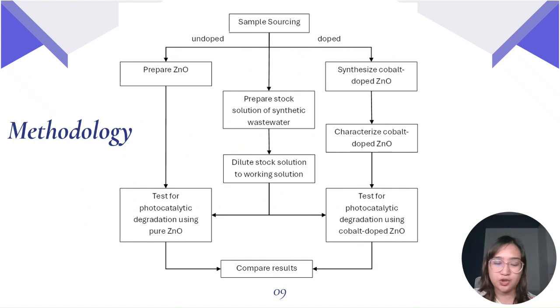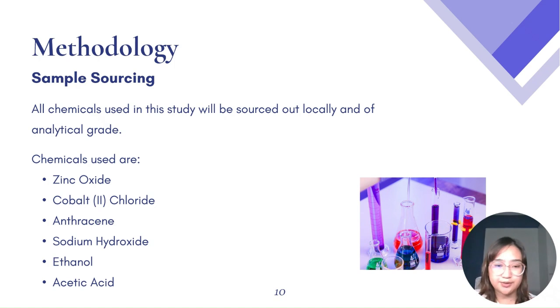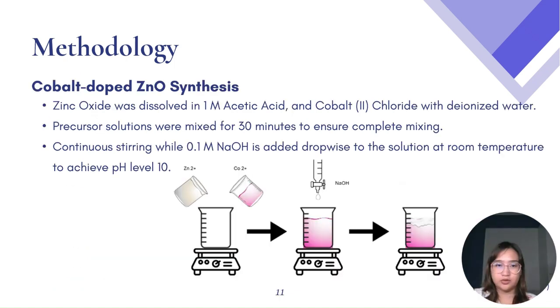The methodology will have the following flow. For sample sourcing, all chemicals used in this study will be sourced locally and of analytical grade. The chemicals used are listed below. To create cobalt-doped zinc oxide nanoparticles, the chemical co-precipitation method will be used. For the synthesis, zinc oxide was dissolved in 1 M acetic acid and cobalt chloride was dissolved in deionized water at room temperature. There are three variations of dopant concentration, 5%, 10%, and 15% by mole, and all underwent the same process, only with different mole concentrations.